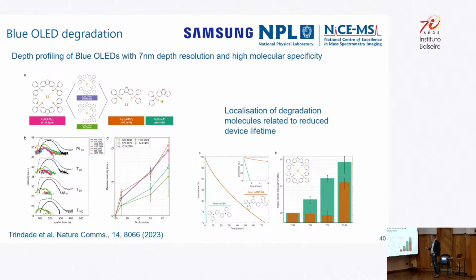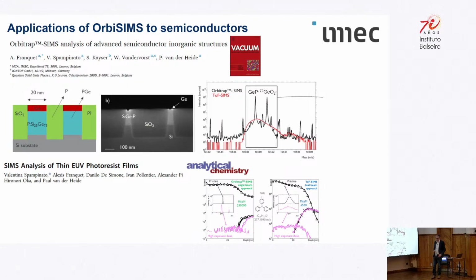But then once Samsung knew what these degradation molecules were, they could change the host chemistry, and then by changing the host chemistry, they could improve the lifetime of the devices by a factor of 10. So this is a really nice example. Samsung actually have 2 OrbiSIMS running all the time for these kinds of applications.